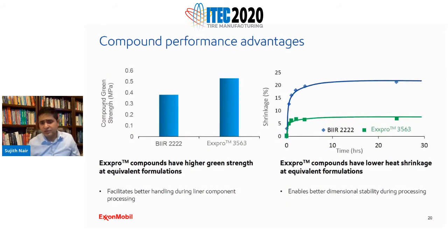One of the other things that we have noticed with Exxpro is that, because of the affinity to carbon black, just because it acts as a better filler, it gives much more reinforcement properties than conventional bromobutyl. We have seen that Exxpro has better green strength, better uncured strength than bromobutyl-filled compounds. This is important because it enables better or easier processing before it goes into a tire and it's cured. It's got around 25-30% improved green strength as opposed to bromobutyl.